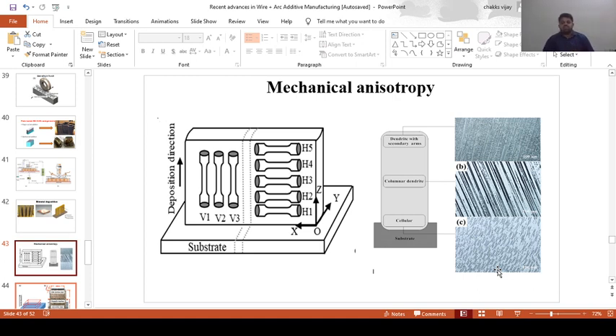So if we want to overcome this, then we have to play with the deposition strategy. We can go for a different deposition strategy, like a zigzag pattern, or a raster pattern, or we can even plan an adaptive path. So with different planning, this kind of coarser grain formation could be greatly avoided. We can obtain a homogeneous grain structure. In order to attain that, we have to play with the path planning strategies.